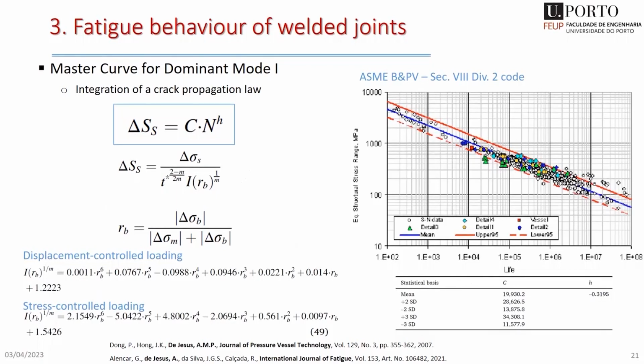The other part is the integration of the crack propagation law. I'm not showing the details here. So a fatigue crack propagation law, which accounts for small cracks and the non-linear stress near the weld toe. That was done analytically, and we derived this concept of an SN curve, where we have a new definition for the structural stress that depends on the size of the component, like plate thickness or crack propagation size, and also information about the stress, the structural stress definition.